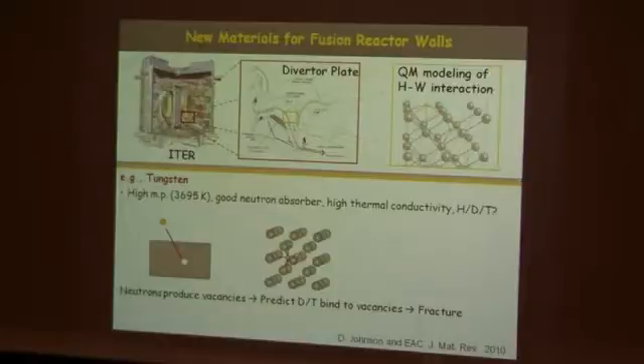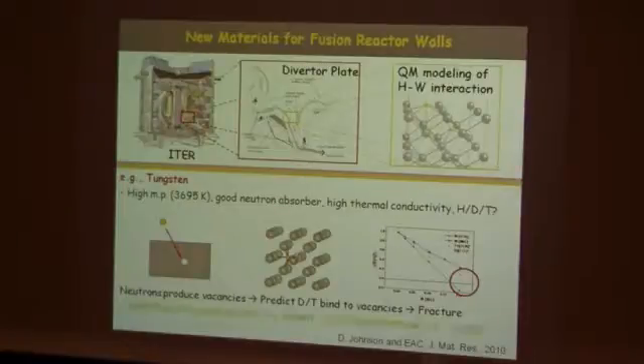Anyway, what we have shown is that these isotopes of hydrogen will in fact bind strongly to vacancies in tungsten. And as a result, we were also able to look at the embrittlement. You can't read this, but this is basically showing the stability of the tungsten as a function of how much hydrogen is there. And when it goes below zero, it's not stable anymore. And so the point is that the hydrogen in the presence of neutrons is going to want to get into tungsten. So there will be important issues associated with how you might alloy the tungsten or anneal the tungsten, heat it up to get rid of those vacancies, to essentially inhibit the formation of the vacancies so that you can inhibit the incorporation of these hydrogen isotopes.